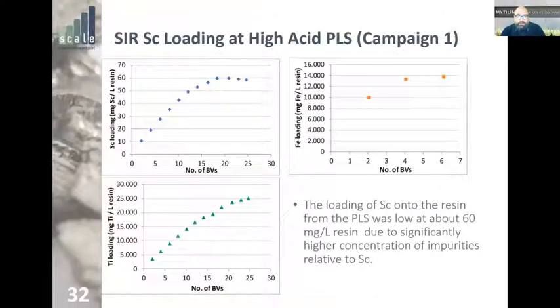So we took this pregnant leaching solution and tested it with the resin. Here these are the loading graphs of the resin. The x-axis is the number of bed volumes. So you have a column packed with this resin, and you start passing the pregnant liquid solution through this column, and you measure the exit of the resin to see the concentration in scandium, iron, titanium, and you measure the number of bed volumes that will pass through the resin.